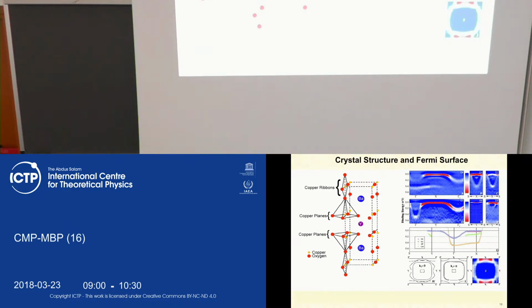And as I said, taking the picture from neutron scattering, for example, and reconstructing the crystalline structure, led to the conclusion that both oxygen and copper form planes. So the first hint was that the superconductivity is quasi two-dimensional, because the main action happens in the copper oxide planes. It also supports the measurement of the Fermi surface done with angle-resolved photoemission, also supporting this argument that the Fermi surface is two-dimensional, kind of cylinders.